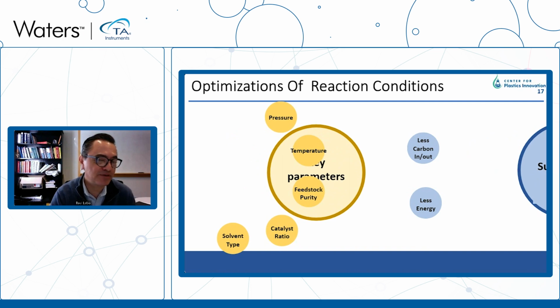And so we are in the process of still optimizing the reaction condition. There's many of them. We want to optimize the pressure, the temperature, understand what the impact of the feedstock purity on the process. The ratio of catalyst to polymer is important, and we haven't found the optimal yet. And what kind of solvents are the best solvents? So in this particular case, we compare C7 to C10 hydrocarbons as the sacrificial solvent. And the heavier solvent has a big impact, we think, because of the solubility at these high temperatures in the polymer is much higher for molecules slightly bigger than C7.